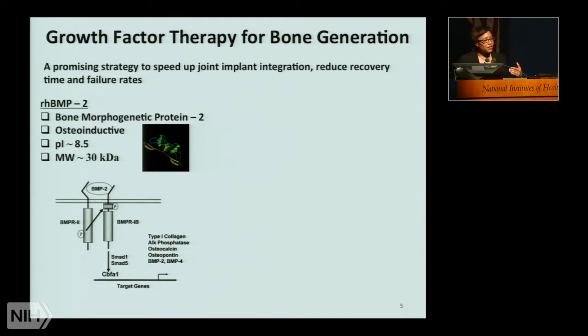What's been the downside of it is that when it is used in the way that it's typically available, a collagen sponge containing milligrams of BMP2, there's a product, for example, that allows a bolus release of this material, you'll get a huge amount of it released into the bloodstream and only a small amount that resides at the site of delivery.